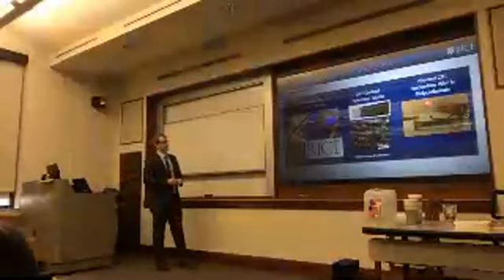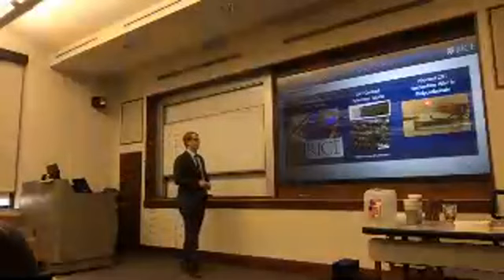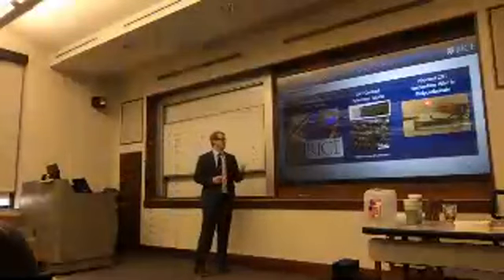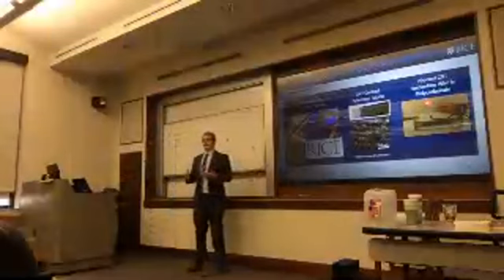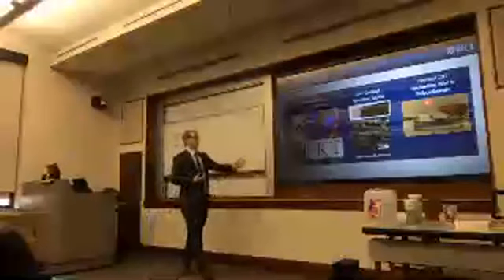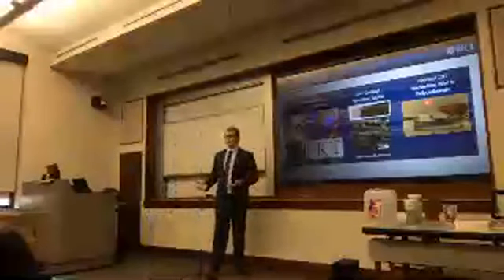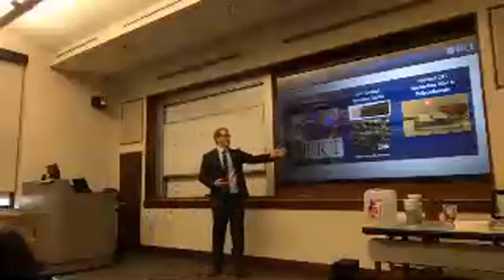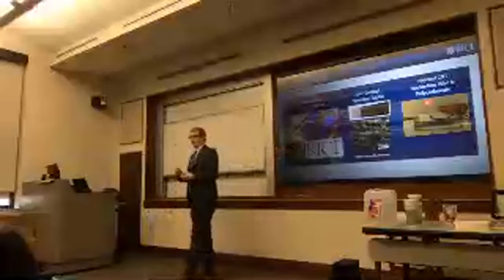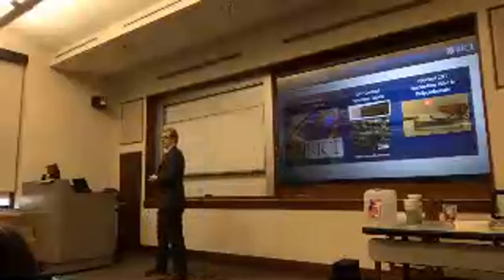So we take this a step further to try to demonstrate the utility of this new acid solvent by benchtop silk screen printing. And in this case, the acid solvent does not damage the silk, doesn't damage the mask, and it doesn't damage the wood. We can also coat polyester fabric, rendering it electrically conductive. And in this case, we have injected a porous carbon nanotube wire into a polycarbonate block that we're now using to light this LED.